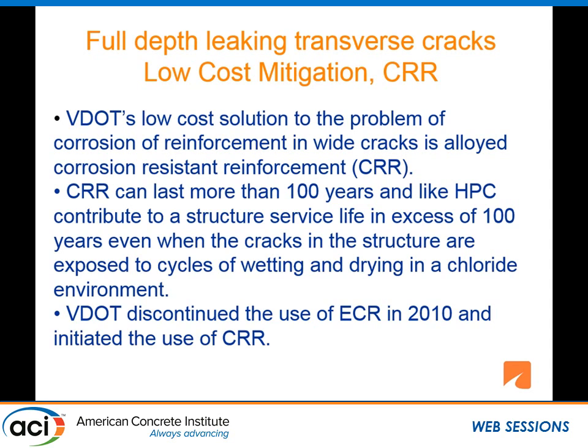VDOT's low-cost solution to this problem is corrosion-resistant reinforcement in wide cracks. Corrosion-resistant reinforcement can last more than 100 years, and high-performance concrete can last more than 100 years. So why not mate it with reinforcement that can last more than 100 years? It just makes good sense. Even when the concrete cracks and the steel is exposed to wetting and drying and de-icing chemicals, if you're using stainless steel or other alloyed steels, you can get bridge decks that will last close to 100 years.